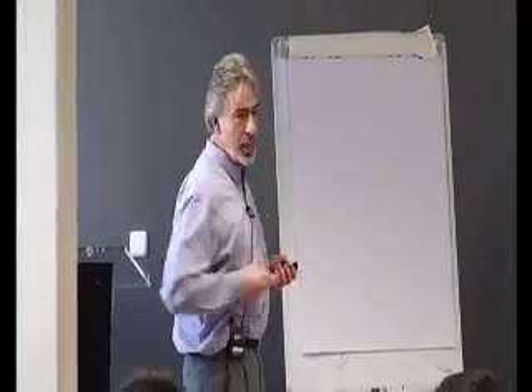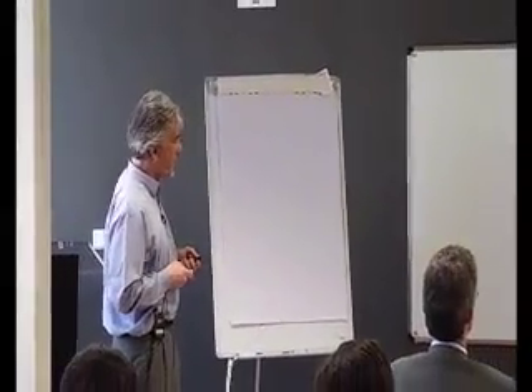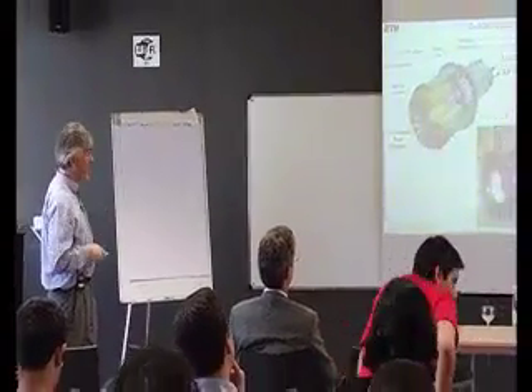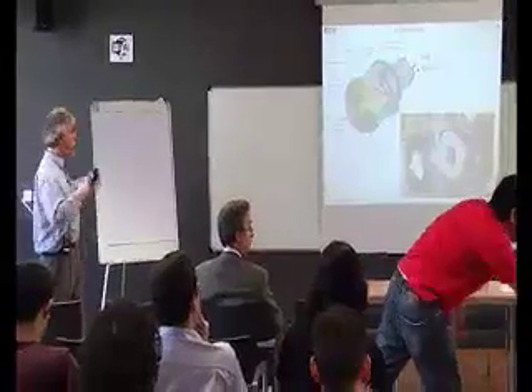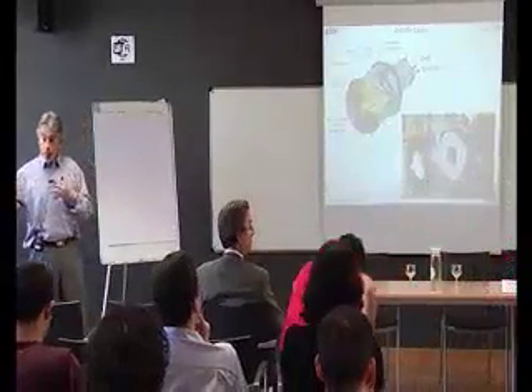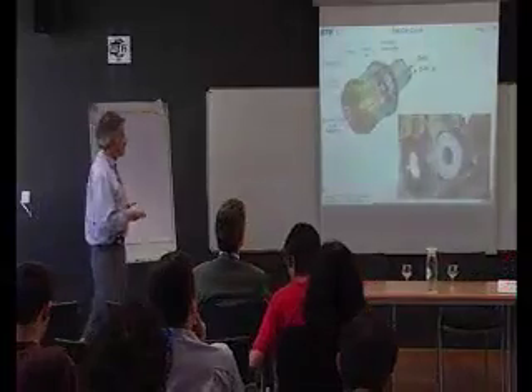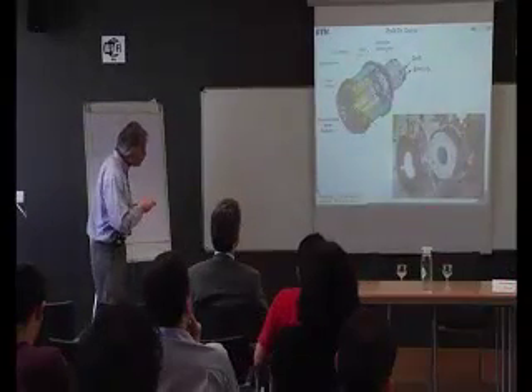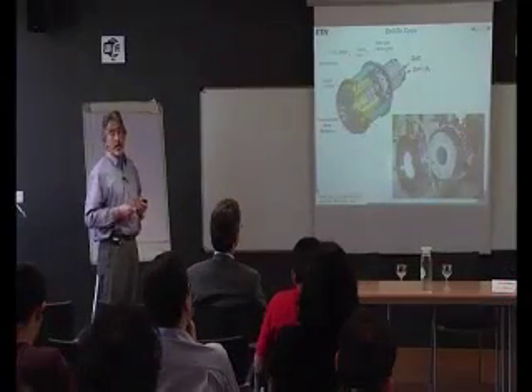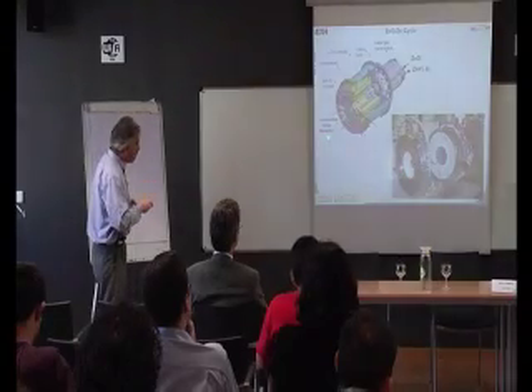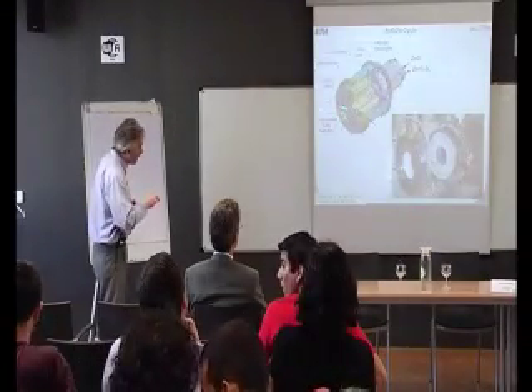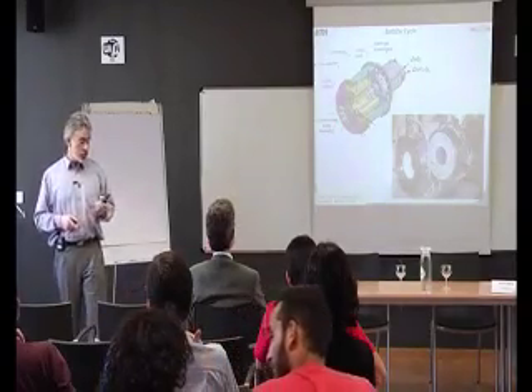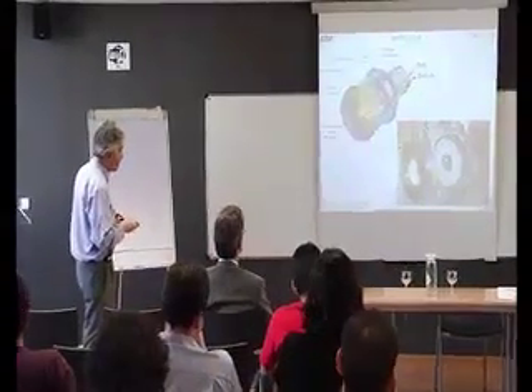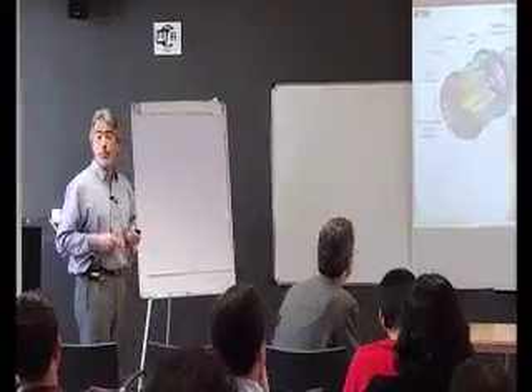Let's look at the reactor technology, and we'll start with the zinc oxide dissociation. This is the schematic of the solar reactor that is being developed at ETH and PSI for the thermal dissociation of zinc oxide to metallic zinc at 2000 K. This is a rotating cavity lined with zinc oxide particles, and the zinc oxide is directly exposed to concentrated solar energy. This is a photograph of a 10 kilowatt prototype.